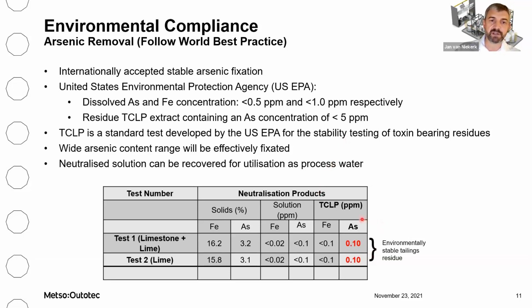Typical results from neutralization tests during bioxidation are shown in the table, and as you can see, the solution concentration of both iron and arsenic following neutralization is well below the standard, as well as the TCLP, or toxicity characteristic leaching procedure, extract following treatment of the precipitate.